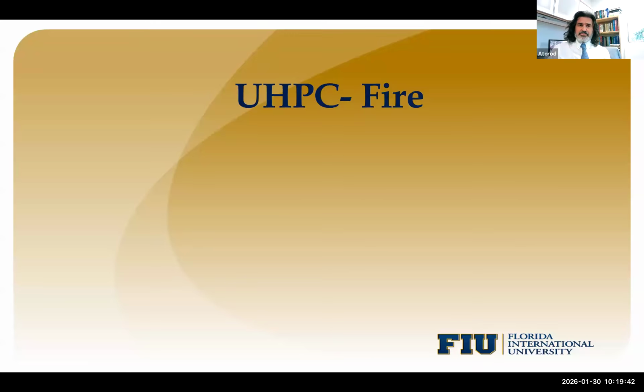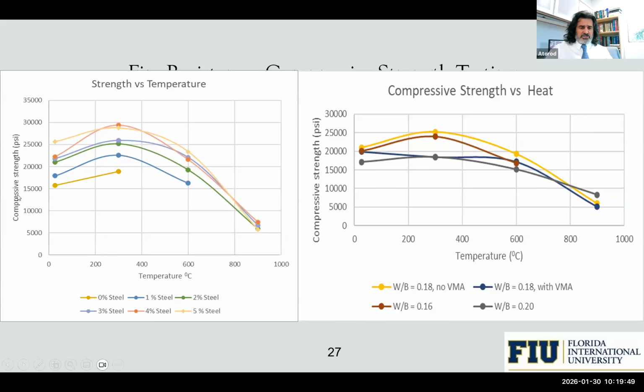We have done a relatively small amount of fire testing, and I can tell you that we don't know the mechanism, but if you heat small cubes of UHPC up to 300 degrees Celsius and then do a compressive test, the compressive capacity actually increases. But if you heat it to more than, let's say, 800 degrees for a couple of hours and then test it under compression, the compressive capacity does go down. Some of our colleagues in Canada called us and they have seen the same thing. There is some explanation for the mechanism, but the work that we have conducted with fire is relatively small.